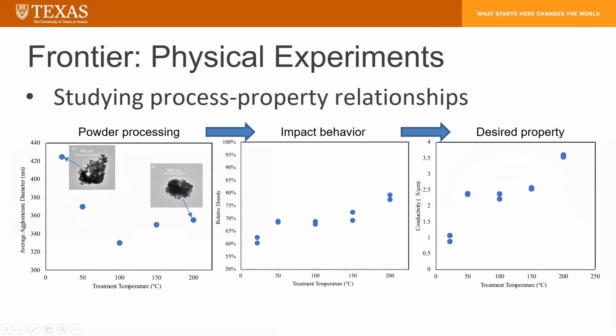This little image right here shows a very loose snowflake agglomerate. And as we increase the heat treatment temperature, the size of the agglomerate drops as it densifies first, and then it actually increases again as multiple agglomerates come together. And so the result is that we're going from snowflakes to snowballs, and then maybe even just ice. What this actually does is it changes how our powders behave in the gas. So it changes what speed they're impacting the substrate, and also changes how they impact the substrate. We can see in this middle plot, as the treatment temperature goes up, which changes the agglomerate morphologies, we actually increase the relative density. So as the heat treatment of the pre-processing changes, we actually get a different relative density of our final result.